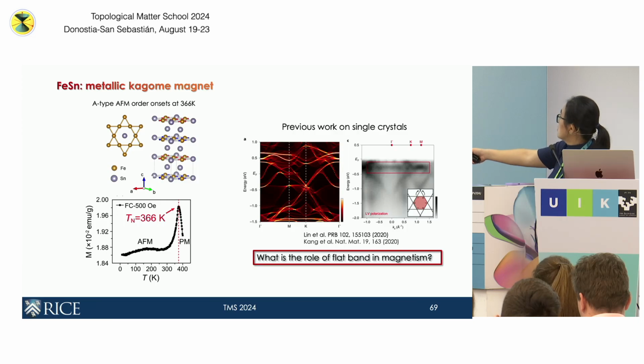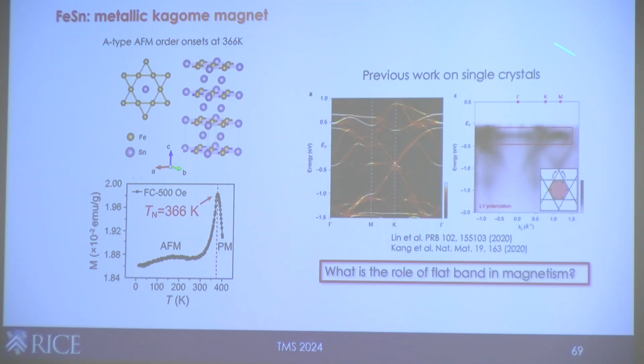There's been previous work on single crystals, but it turns out that the ordering temperature for iron tin... Sorry, let me talk about magnetic structure first. The magnetic structure for iron tin is A-type AFM. So within each layer, the moments are ferromagnetic, and then they're anti-aligned in the stacking direction, right? The ordering temperature is a bit high, but not unreachable. Previously there's been a lot of work on single crystals, but it's very difficult to track the single crystals across this ordering temperature because the sample dies before you get there.